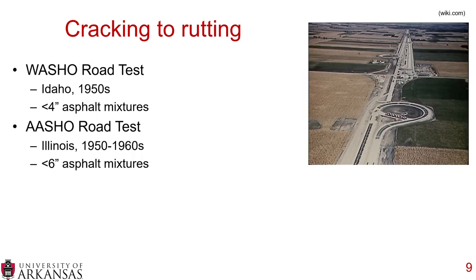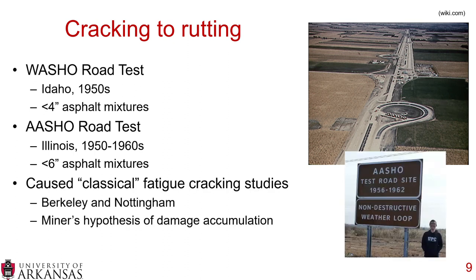Moving on to the 1950s and the 1960s in Illinois, the AASHO road test, note how there is no T in that in the 1950s and 1960s, that's not a typo. And all of the tests there used less than 6-inch asphalt mixture lifts or thicknesses. And what happened is these two tests really caused what we can consider the classical fatigue cracking studies. And the two biggest ones came out of UC Berkeley and Nottingham over in England. And both of them revolved around the Miner's hypothesis of damage accumulation. And I do want to point out that I was lucky enough to visit the AASHO test road site. It was quite the event in Ottawa, Illinois, and I'm very proud to have been there.